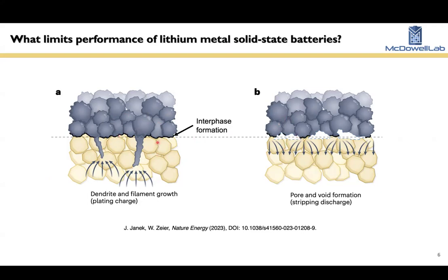The other major problem occurs when you're discharging the battery instead of charging the battery. And it's the fact that when you have a solid-solid interface, lithium metal, as you strip it, as you oxidize lithium and remove the ions through the solid electrolyte, it has a tendency to form voids and pores at the interface. And this is also really bad. It causes a higher impedance. It causes current concentrations at regions that still contact, like right here. And then when you try to recharge the cell, you grow lithium at these contacting regions, and it causes very high local current densities, which induces filament formation. So these two processes are related.